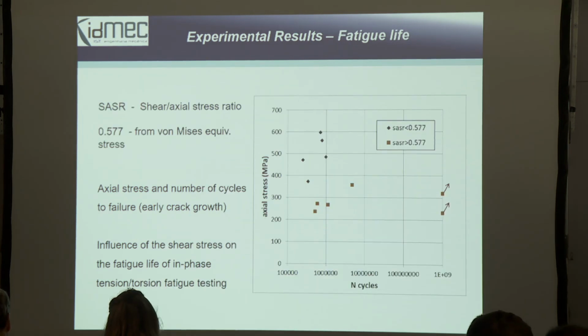And okay, some results. We have put here the axial stress, because it is the one that is always constant between the three specimens. So we have divided this where the shear to axial stress ratio is higher than the equivalent von Mises equivalent stress, or is lower. And we have two different behaviors. We could not have many tests over there for 10 to the power 9, because we only have a few tests yet. This is a study that is ongoing, but we see different behavior with this.